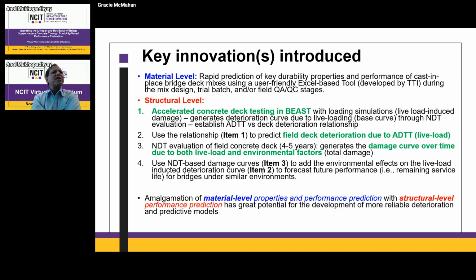And then the structural level, Rutgers is leading that. They did accelerated concrete bridge deck testing in BEAST, and they developed the deterioration curve due to live loading only through NDT evaluation, and established a relationship between the ADTT and the deck deterioration. That relationship we use to predict the deck deterioration due to ADTT live load in item 2. Item 3, they did a significant amount of NDT evaluation in a couple of bridges over a duration of 4 to 5 years. They developed a damage curve over time due to both live load and environment.